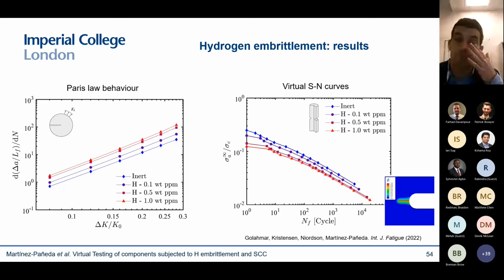Other things that we can do is that we can predict Paris law behavior. And I should emphasize here that Paris law is not an input to the model, it's an output. We model cycle by cycle in these models, which means that we are able to capture arbitrary loading history. So we can capture the effects of arbitrary loading histories, and we can take as an output of the model the Paris law parameters, and of course the influence of hydrogen on these Paris law parameters. And we can also do virtual SN curves for, as I said, arbitrary loading histories or complicated geometries, or arbitrary geometries, basically. You can see it here for a notch sample and for different hydrogen concentrations.